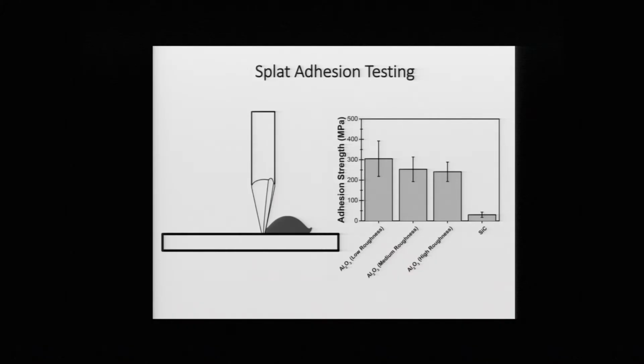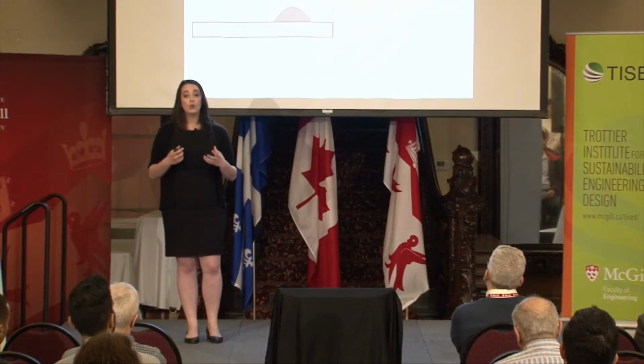And the results we've seen were actually quite interesting. The adhesion was higher to the low surface roughness aluminum oxide than to the high surface roughness aluminum oxide. And this is kind of counterintuitive, because if the bond was only mechanical, you would expect that with more surface roughness, it would kind of be clamped in there. But that's not what we're seeing. It's not giving a higher bond strength.